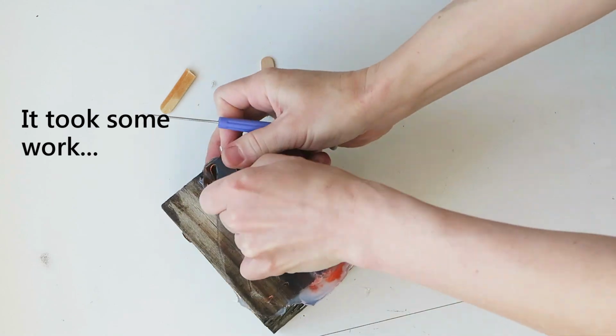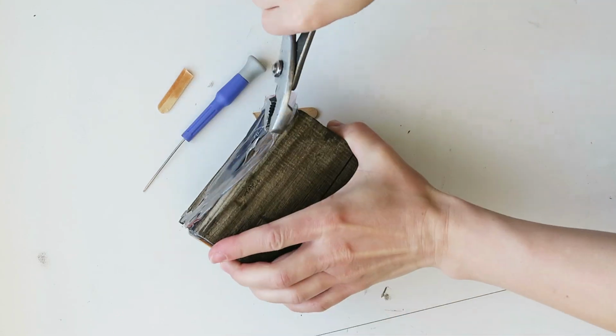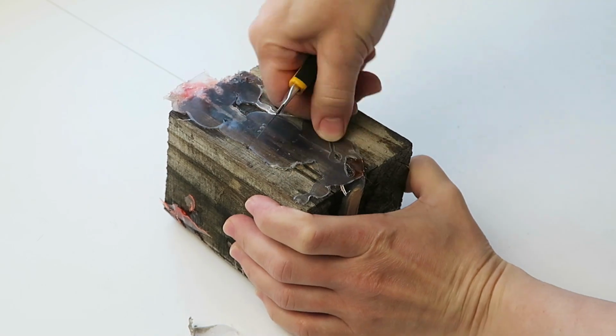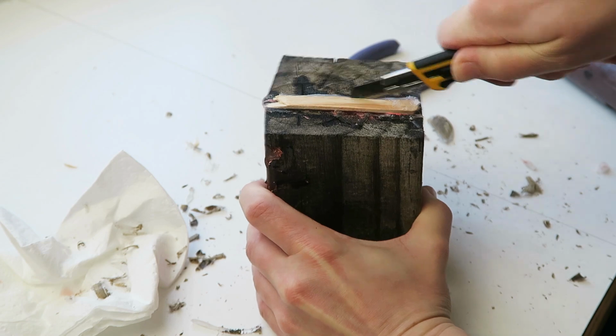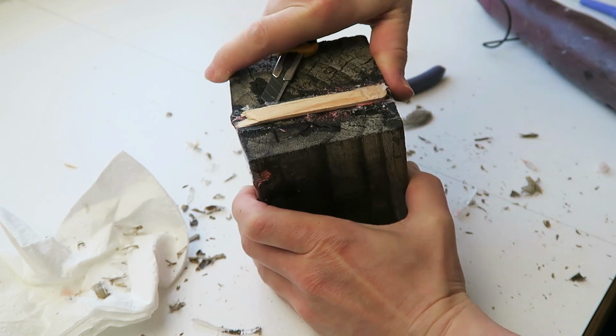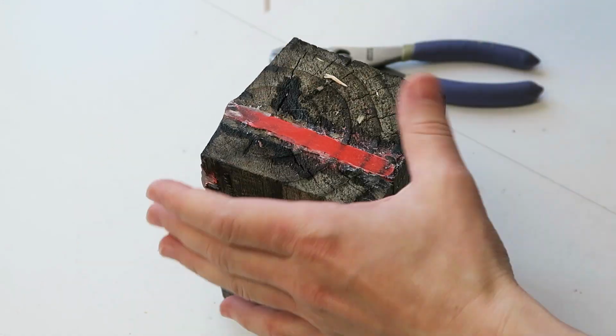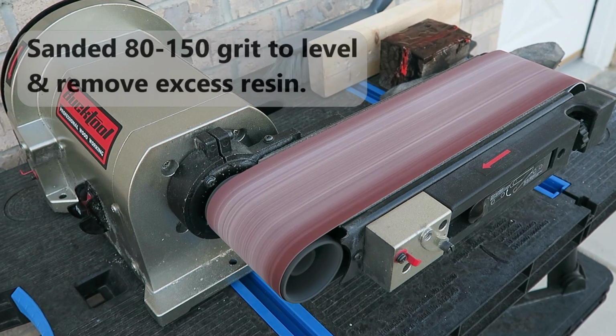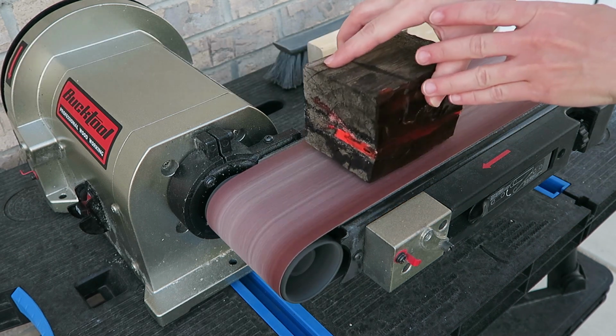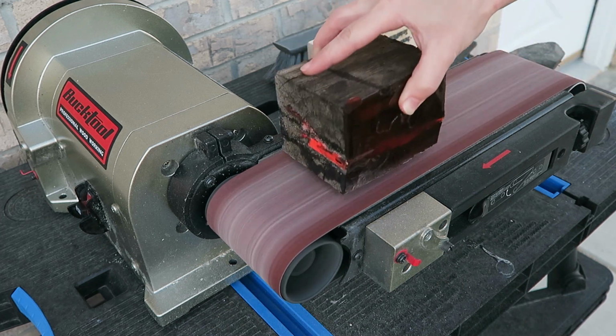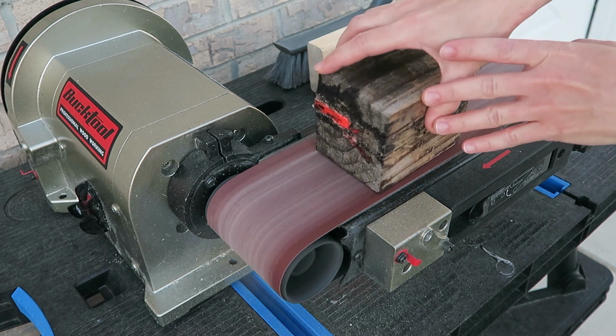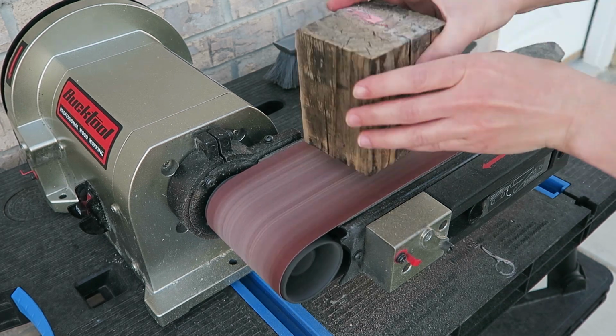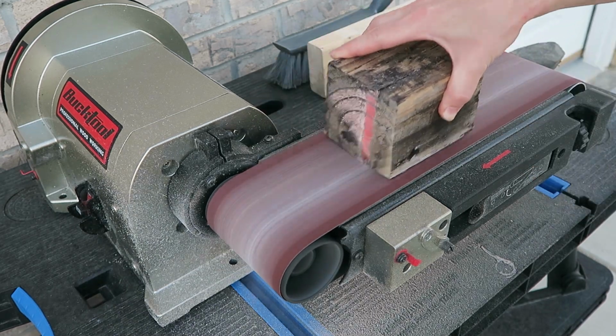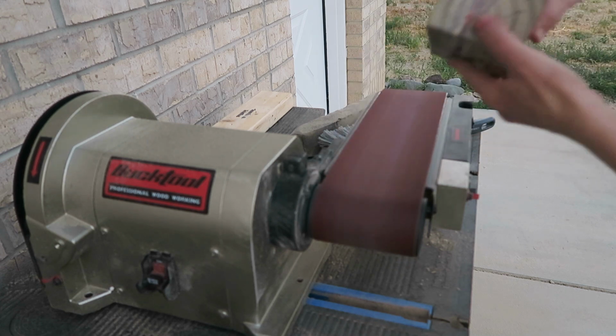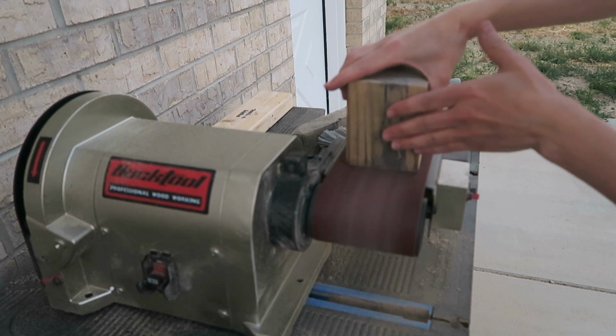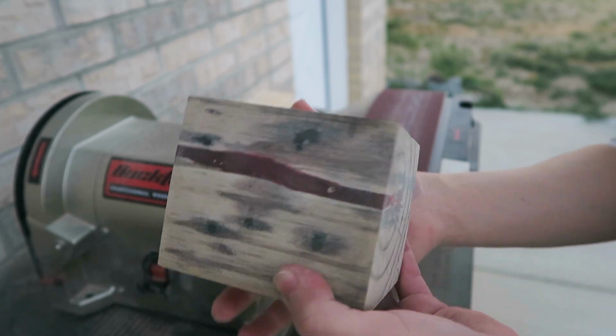The hot glue was kind of difficult to remove from the wood, but I managed to scrape and peel it all away, and any surface damage was about to be removed on the belt sander anyways. The belt sander was the perfect tool to flatten out the overfilled resin and smooth and level all the sides. This is where I uncovered some air pockets caused by the partially cured resin, so these will need to be filled later on.